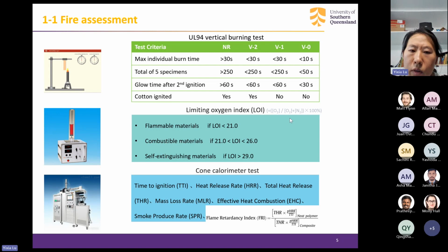The second test is LOI, which means limiting oxygen index. For flammable materials, the value is lower than 21%. And for combustible materials, the value is between 21 to 26%. This is not safe as well. For self-extinguishing materials, the value is over 29%. This is much safer. We also use the cone calorimeter test with so many parameters like time to ignition, heat release rate, and mass loss rate to evaluate the fire safety.